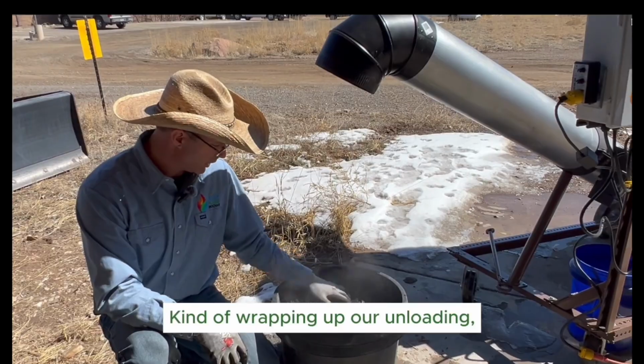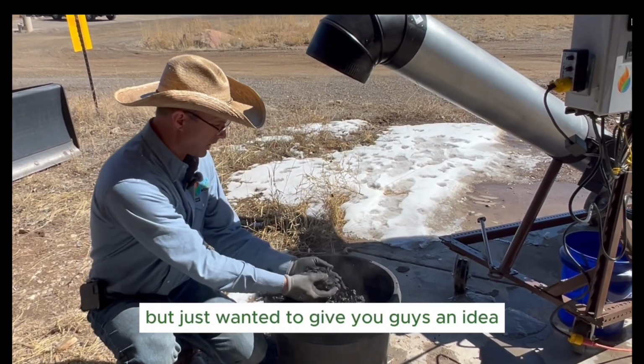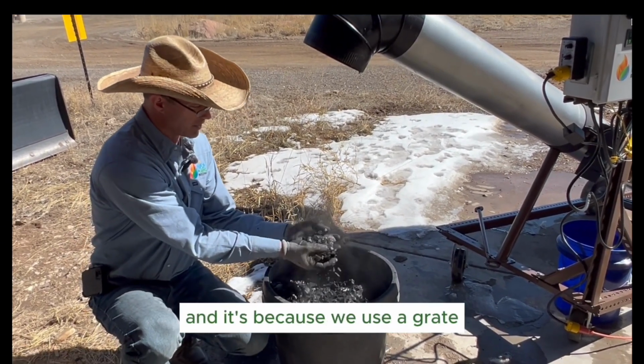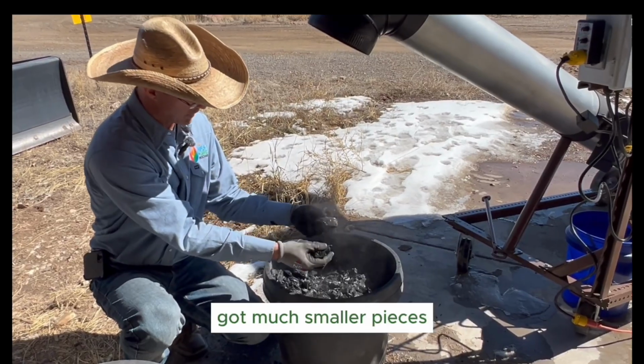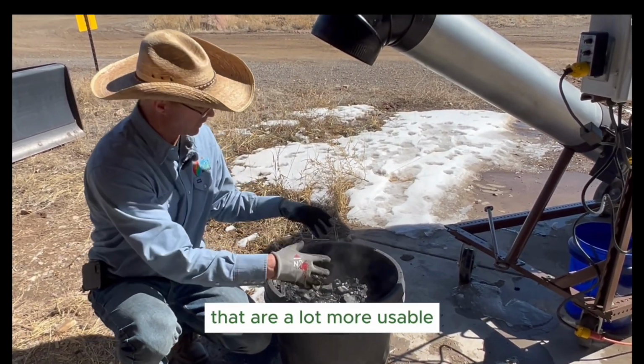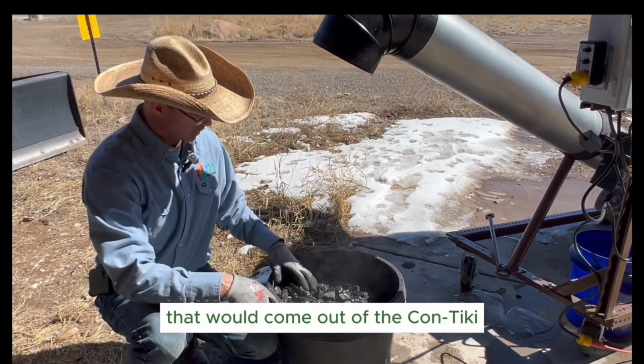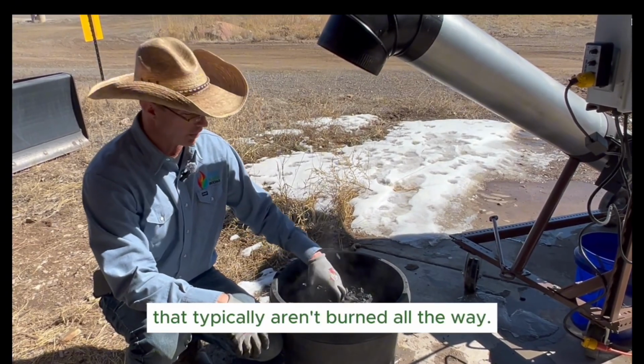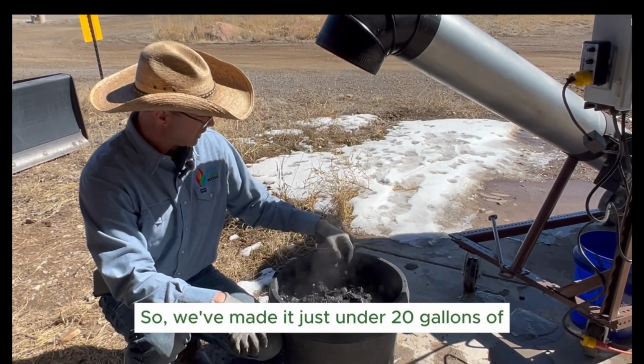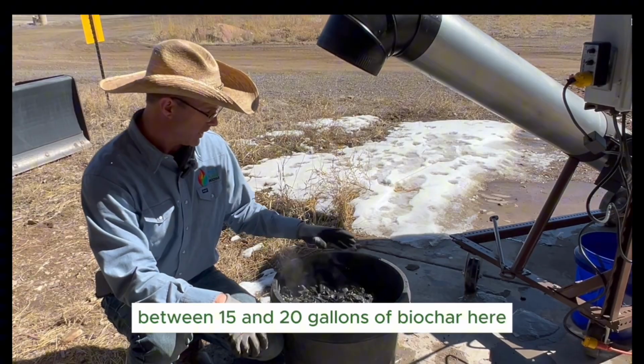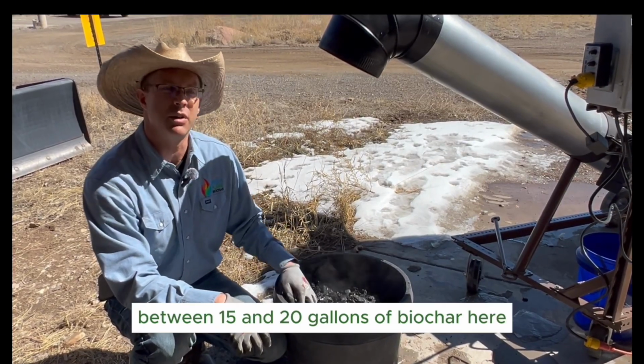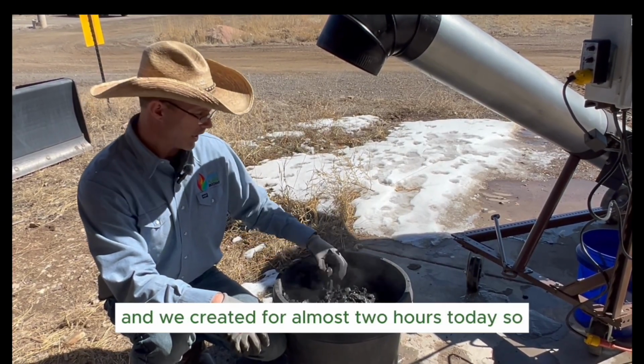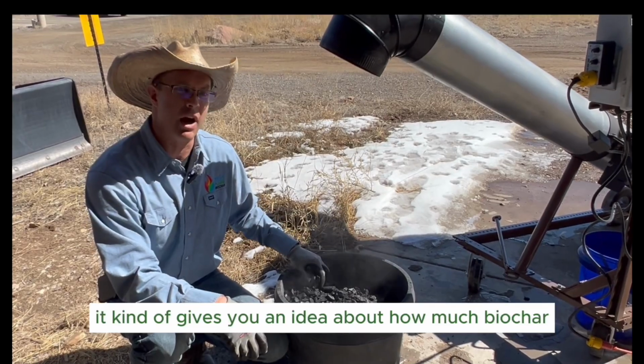Kind of wrapping up our unloading. Still got a few more pieces coming out, but just wanted to give you guys an idea how this comes out. It's quenched, and because we use a grate, we've got much smaller pieces that are a lot more usable than some of the other big chunks that would come out of a Kontiki that typically aren't burned all the way. So we've made just under 20 gallons, between 15 and 20 gallons of biochar here. We've been running for almost 2 hours today. So it kind of gives you an idea about how much biochar this makes.